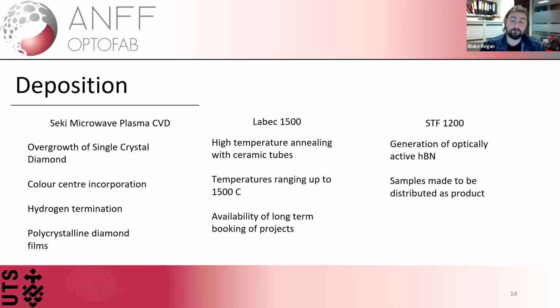So long as your sample won't cause undue contamination to the chamber that would negatively impact our diamond growth, I'm quite happy just to allow people to come in and open up the use of this hydrogen for other non-diamond related purposes. And as much as I detail my growth to stand away from polycrystalline diamond, I am perfectly capable of creating polycrystalline diamond films, which we've done for projects, including one with Switzerland, where we just simply needed to coat and seal the end of a capillary tube with the use of diamond as an inert material that was also quite strong and resistant.